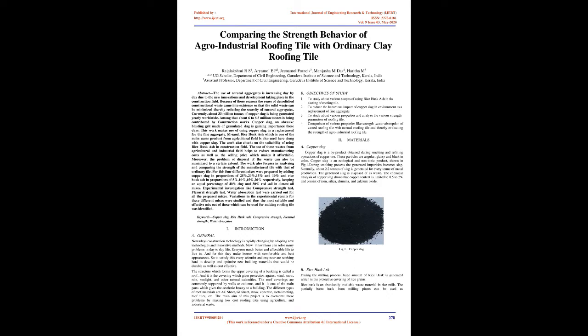Materials. Copper slag. Copper slag is a byproduct obtained during smelting and refining operations of copper ore. These particles are angular, glassy, and black in color. Copper slag is an ecological and non-toxic product, shown in Fig. 1. During the smelting process, the generated impurities become slag. Normally, about 2.2 tons of slag is generated for every ton of metal production. The generated slag is disposed of as waste. The chemical analysis of copper slag shows that copper content is limited to 0.5 to 2% and consists of iron, silica, alumina, and calcium oxide.